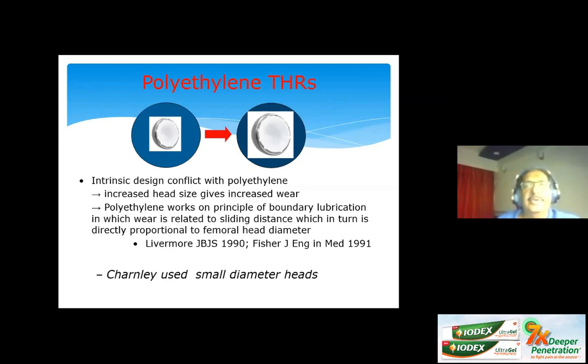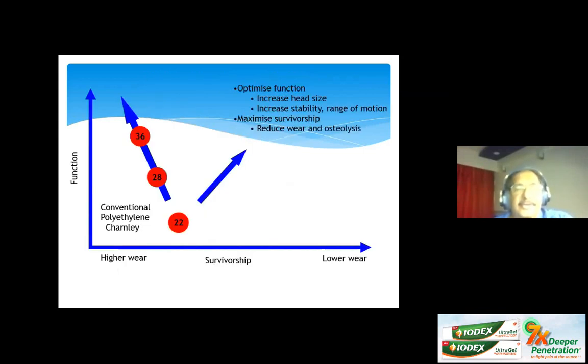Now, when Charnley started doing his hips with the polyethylene that he had, his principle was that as the head size increases, the lubrication, which was the boundary lubrication type, directly related to increased wear of the polyethylene. And that is how his philosophy of using a smaller head, what he referred to as the low friction arthroplasty, came about. Now, our aim is to increase the head size, but if you use a conventional polyethylene with an increased head size, as shown in this graph, the higher wear is a deterrent, and we are not going to get the benefits we set out to get.